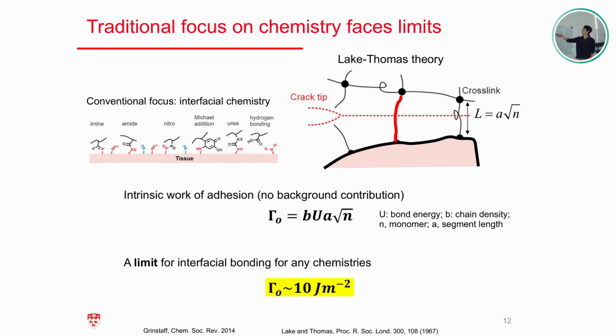Essentially, the energy you need to cleave those bonds is proportional to the length of the polymer chain in between, because when you rupture one bond, as experiments and simulation results show, you need to dissipate all the strain energy stored in the whole chain instead of a single bond. It is also proportional to the energy of the chemical bonds along those chains.